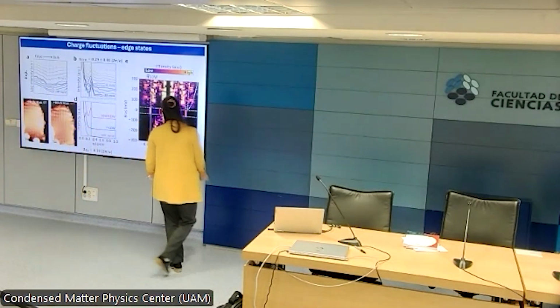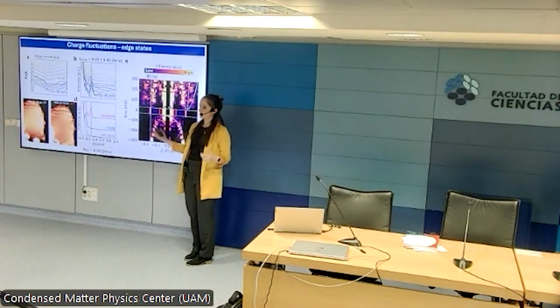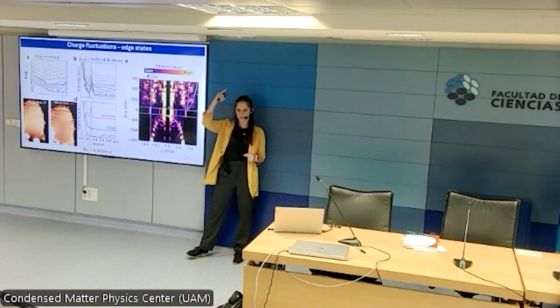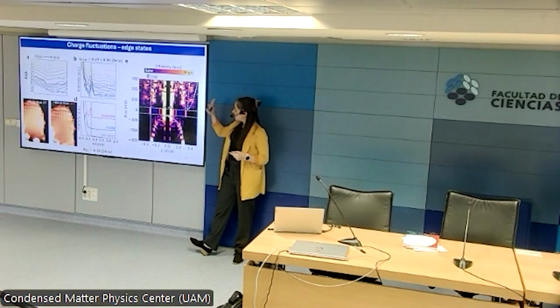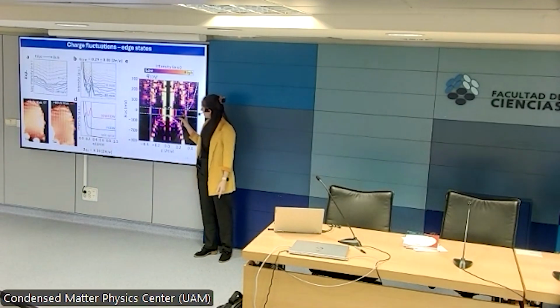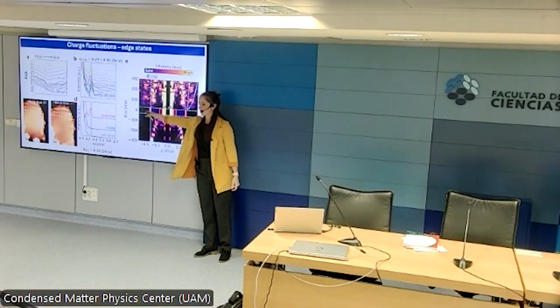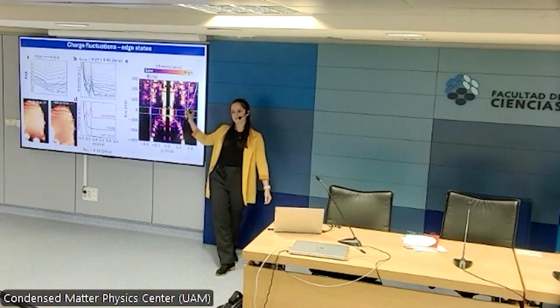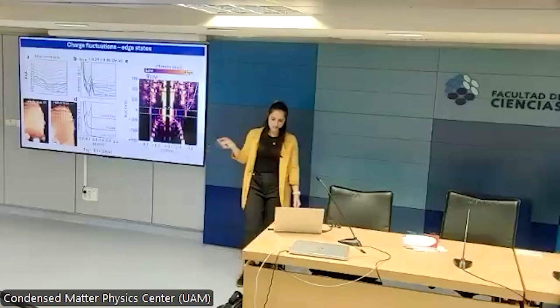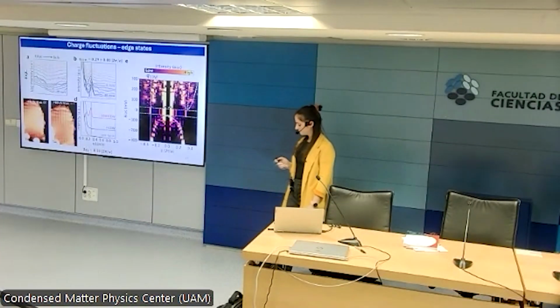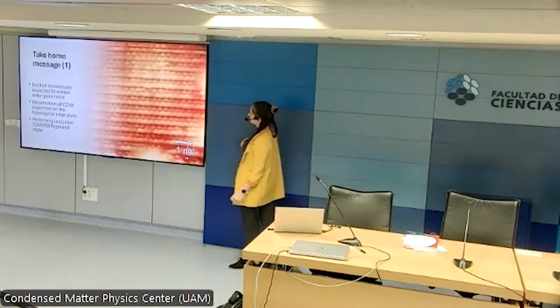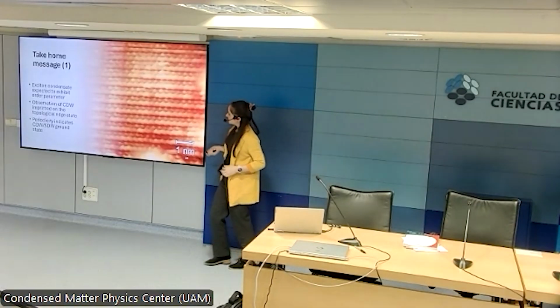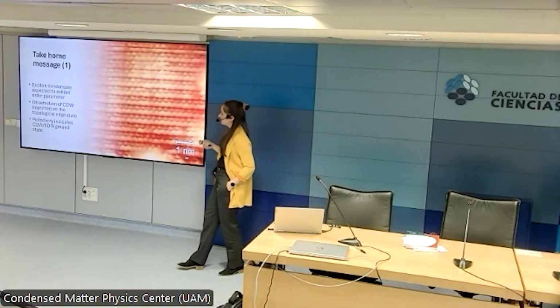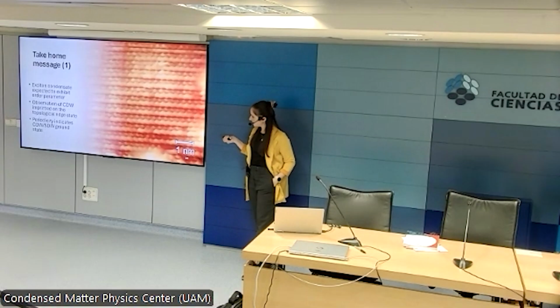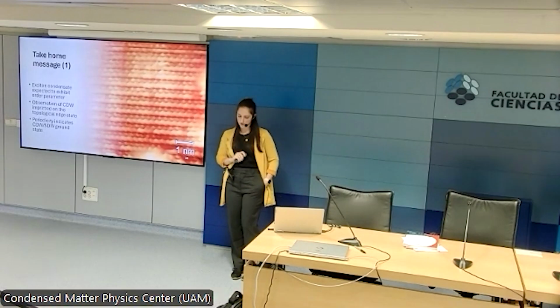Last bit of evidence on this. If you remember, I showed you these maps done by cutting away the 2 nanometers that are at the edge. If you include the edge in the 2D transform, you see in the bulk band gap the appearance of these modes, which are very vertical and very non-dispersive, and these correspond, indeed, to the frequency of the charge density wave. So I hope that I've convinced you with this that the exciton condensate indeed is expected to exhibit another order parameter, that we see a charge density wave, and the periodicity tells us which ground state we are in.